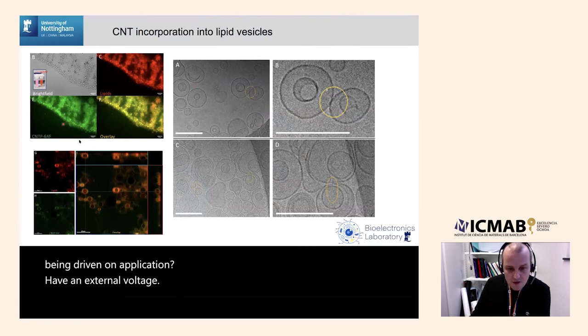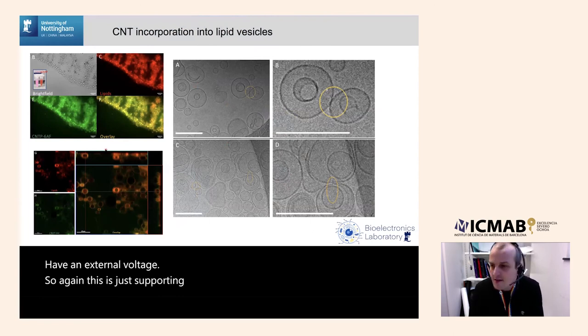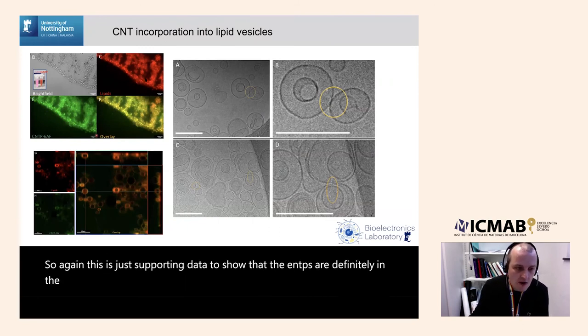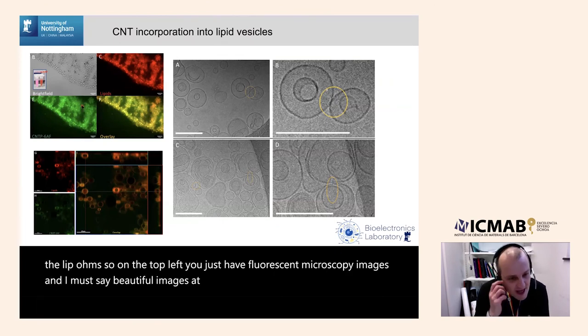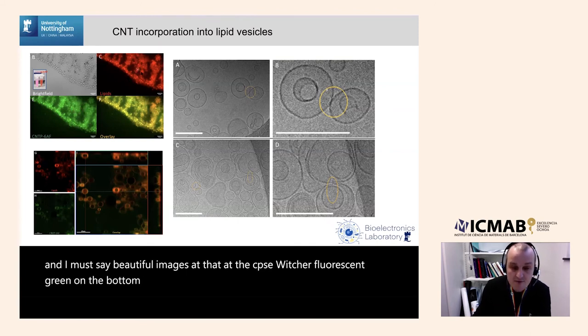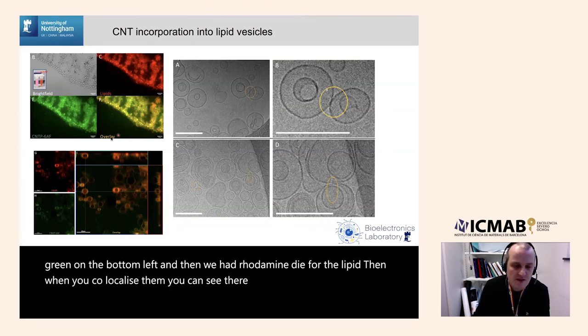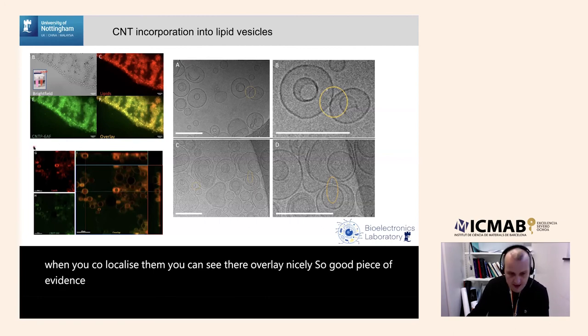So again, this is just supporting data to show that the CNTPs are definitely in the liposomes. On the top left, you just have fluorescent microscopy images, and I must say beautiful images at that, of the CNTPs, which are fluorescent green on the bottom left. And then we had a rhodamine dye for the lipid. Then when you co-localize them, you can see they overlay nicely. So good piece of evidence, CNTPs are in the vesicle membrane.